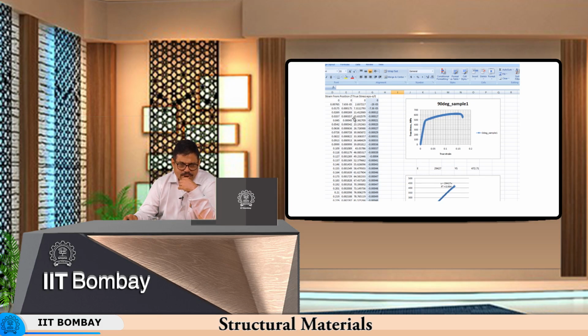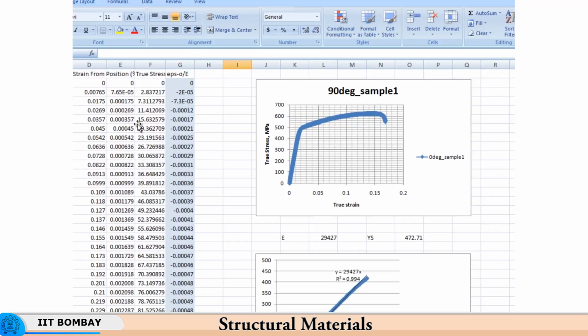These two are my sigma by E. So, epsilon minus sigma by E is my plastic deformation which has been retained, and I say that the material has yielded when this plastic deformation which is retained reaches 0.2%. 0.2% is the plastic deformation that has been reached. So, that is the 0.2% proof stress.